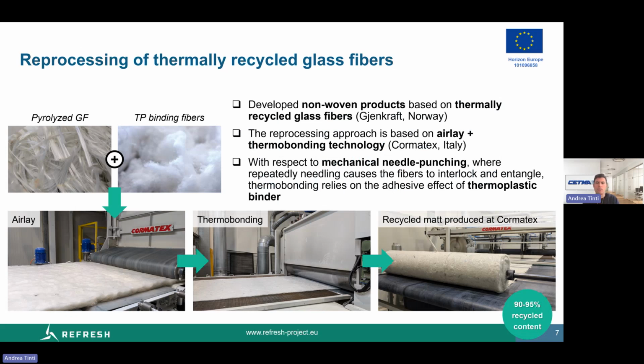First of all, a non-woven product, a non-woven mat in particular, was developed based on thermally recycled glass fibers. The processing approach was based on an airlay and thermobonding technology, thanks to the collaboration with the Italian company Cormatex. With respect to traditional needle punching, thermobonding relies on the adhesive effect of a thermoplastic binder. So this can help when using recycled fibers, where the thermal treatment at high temperature could have caused material embrittlement.